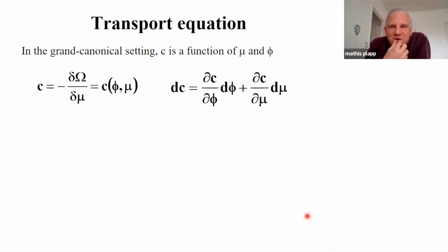Now, for the equations of motion, we have to do the same thing as before, but now for the concentration. The concentration is now a dependent variable. It depends on the phase field and on the chemical potential. So if I take the variation of the composition, this is now a function of the variations of the phase field and of the chemical potential. This derivative here, I call chi. It's actually a generalized susceptibility.